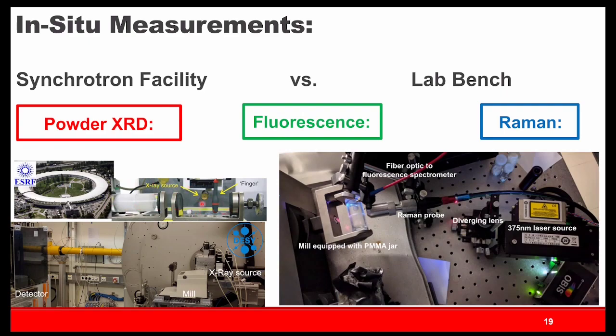But in this case, we have the X-ray source of a synchrotron, which is shown here. It's coming out of this tube, which is here. And we shoot the beam through the milling jar and collect the diffraction signal on the detector. And this gives us information of what the crystalline phase is at any given time during the reaction.